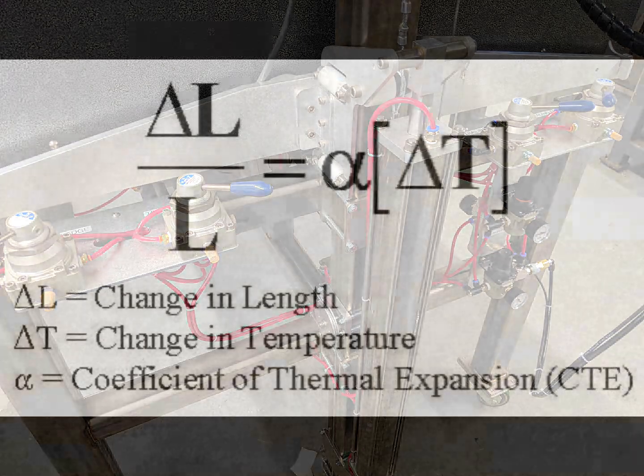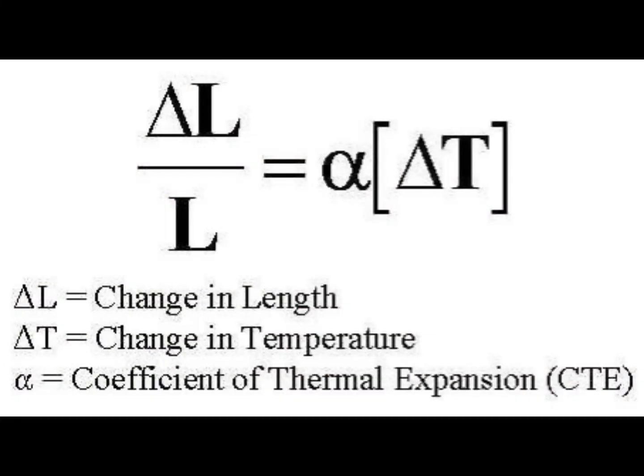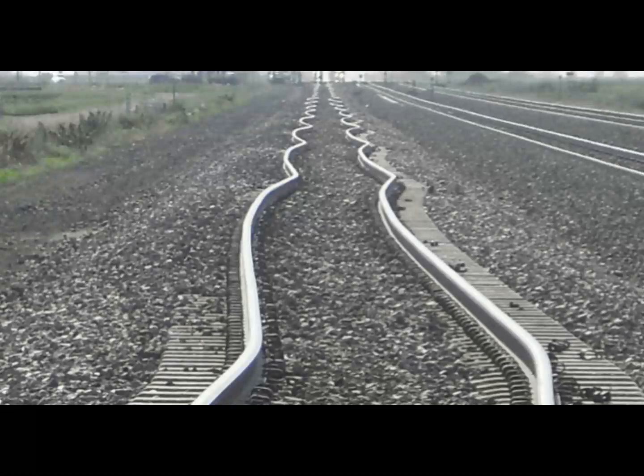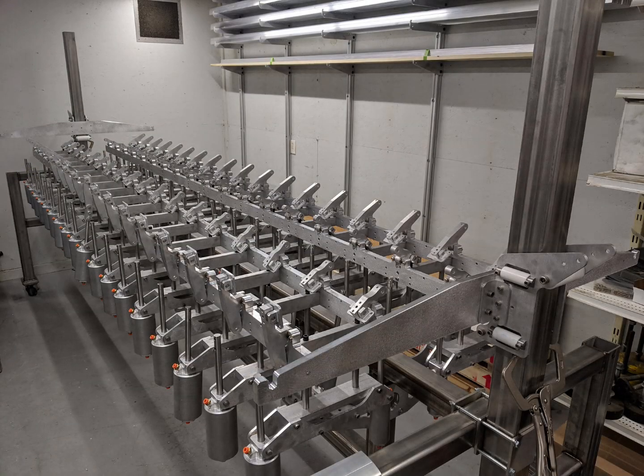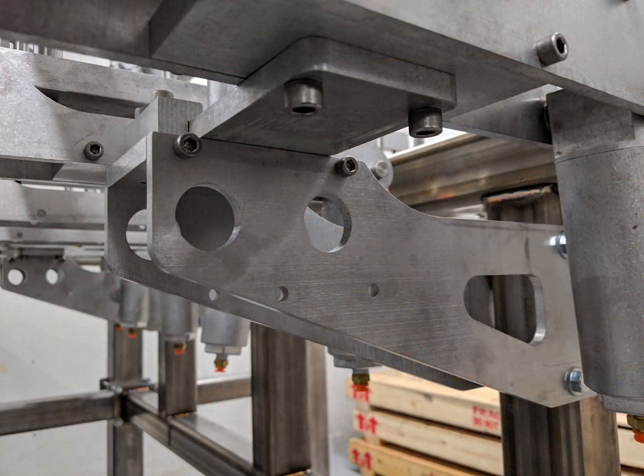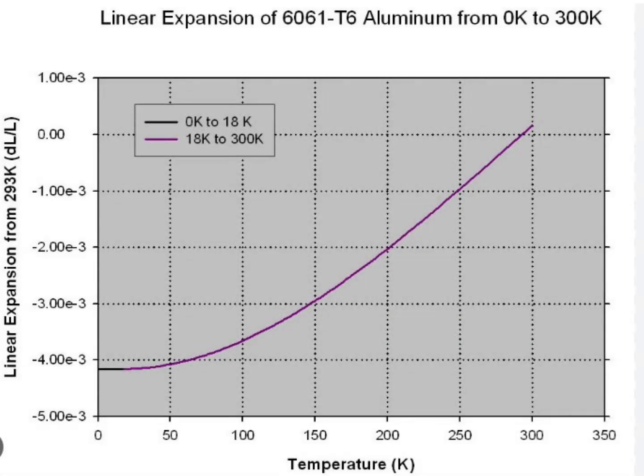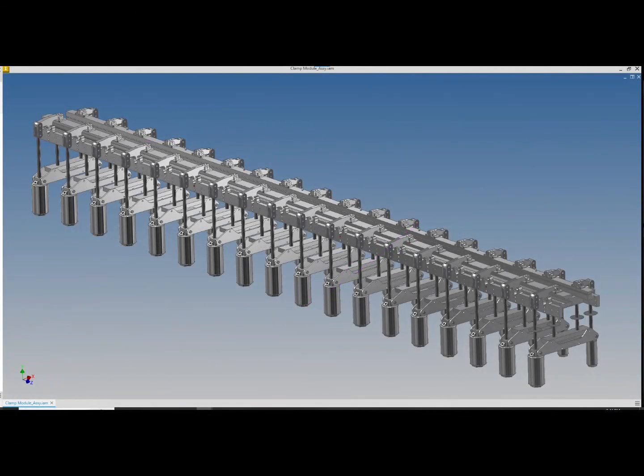The other major consideration in the design of the curing oven is thermal expansion. From ambient room temperature to cure temperature, a 12-foot blade will expand almost 300 thousandths of an inch, or 7.5 millimeters. Because of this, only the center is rigidly mounted to the frame, while the outer sections are allowed to float in some slides while the material expands as it heats up. The parts in the oven are made from the same alloy as the blades, so they have the same coefficient of thermal expansion. And during the heat cycle, everything expands and contracts together evenly, removing any chance of any shearing forces acting upon the adhesive bond.